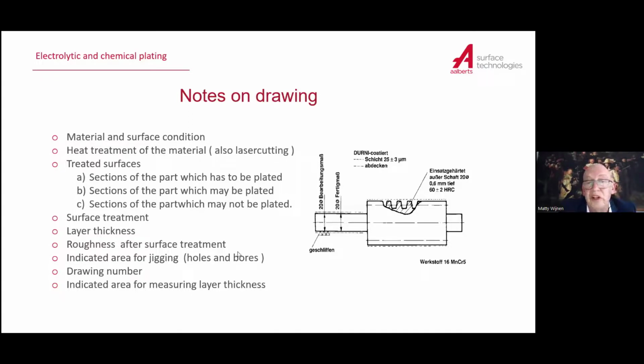Then we have to know, because what you saw is that all the parts are dipped, immersed in baths and in tanks. And in some of these tanks, we make also electric contact to the bath. Also in chemical plating or in conversion plating, we have electrolytic processes. So what's important is that we have a contact part. Where can we clamp the part, and where can we make contact with the part? That's something which has to be on the drawing, because on that spot, you don't have your coating.